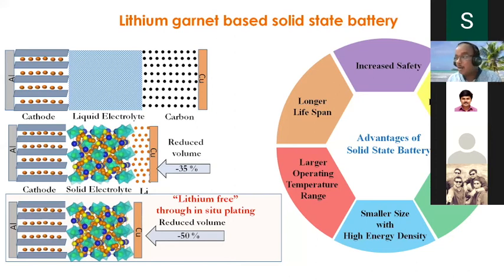Which means that the biggest problem people face in the industry is how to handle the metallic lithium, how to get this thin layer of metallic lithium. Very difficult. Now things are completely changed. This strategy has been completely changed. Pushing lithium from the cathode side and making metallic lithium at the anode during the plating.